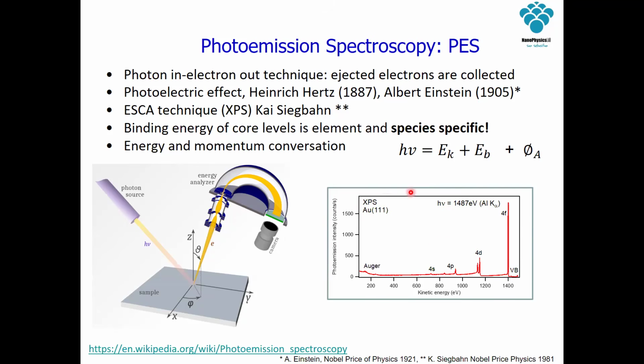So here we see one spectrum that we took in our lab. It's a gold 111 crystal, and this is what we measure inside of our electron analyzer. We have different levels, inner levels, for example the 4f of the gold, 4d, 4p, and so on. And if we had platinum, for example, all these lines would shift a little bit left or right. And if we are able to measure the Fermi energy here, then we can address them, and we know, for example, this is gold.